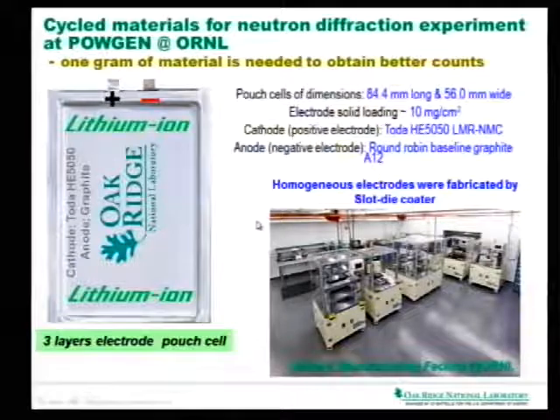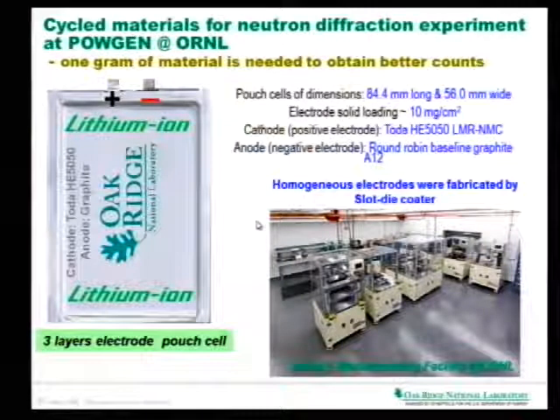Now the tricky thing is neutrons are very penetrating. They don't have a charge. They go very deep. That allows us really a lot of that good characterization, but they also need a lot of materials. And that's why we are currently on the forefront of doing that research, because the amount of material available cycled on that experimental material is very limited. You need about 1 gram of material minimum. I feel more comfortable if we have 1.5 or 2 grams of material.